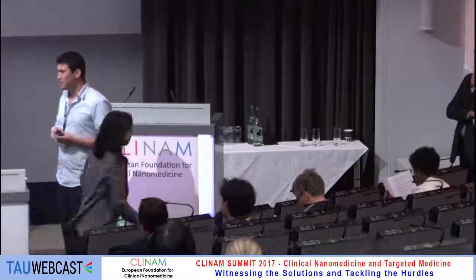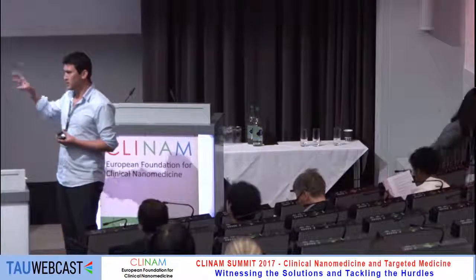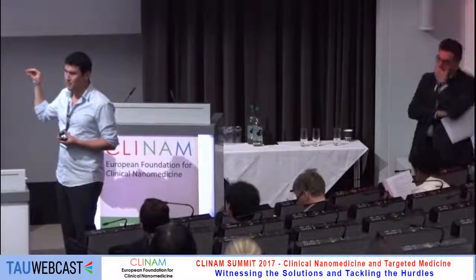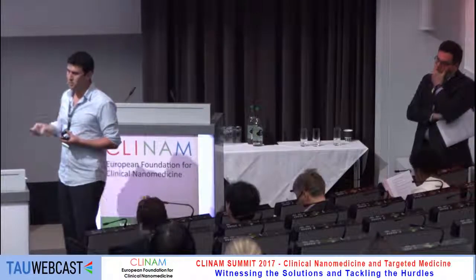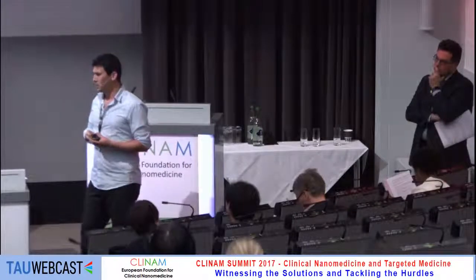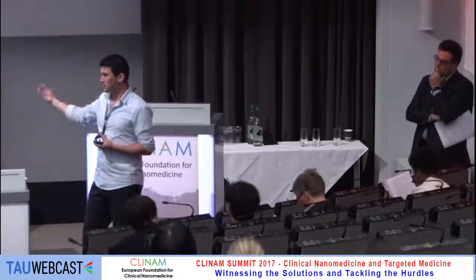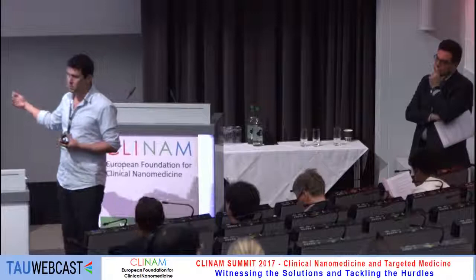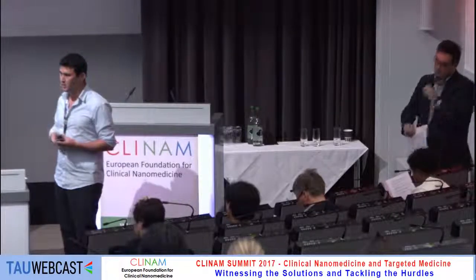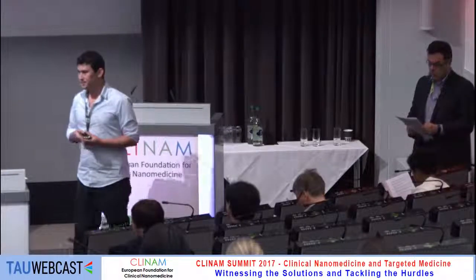What was maybe more interesting was that this effect was very drastic with a PVP polymer coating, but it's minimal if you use, for example, polyethylene glycol or PVA. But the reason we were more excited to use the PVP is because we had more particle uptake. So with a PEG, you have this shielding effect, and then we see very little uptake anyway. I hope this answered the question.